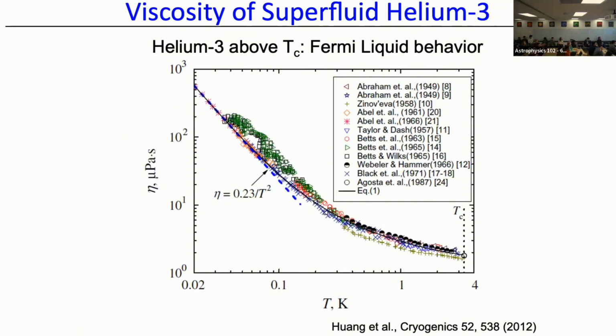Very different story. At low temperatures, the viscosity of helium-3 becomes extremely sticky. It starts out when it becomes liquid at a level which is ħ/m, already the quantum limit, basically, or on the scale of the quantum limit. But then it keeps growing like 1/T². That's because of Pauli blocking of collisions. You start forming a better and better Fermi sea, which has a width given by the temperature. And so only those guys near the Fermi surface still contribute to scattering, and that gives you a viscosity that goes like 1/T². So it becomes extremely sticky.